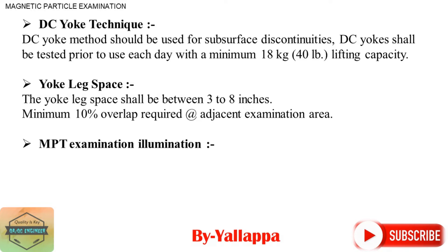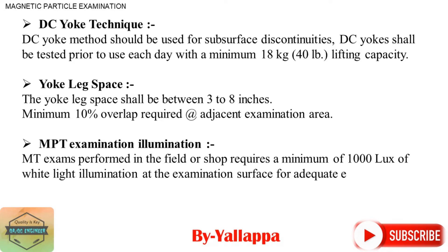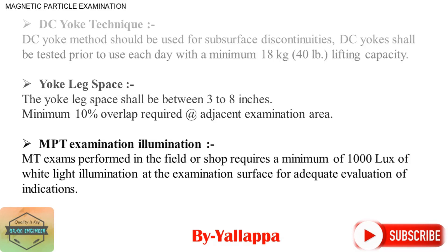Yoke Leg Space: The yoke leg space shall be between 3 to 8 inches. A minimum 10% overlap is required at adjacent examination areas. MPT Examination Illumination: MT exams performed in the field or shop require a minimum of 1,000 lux of white light illumination at the examination surface for adequate evaluation of indications.